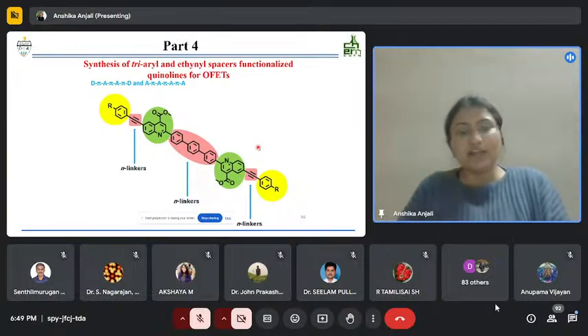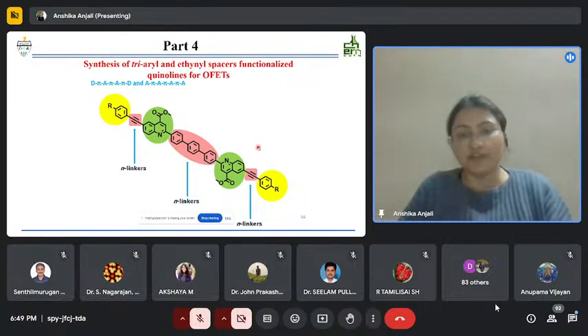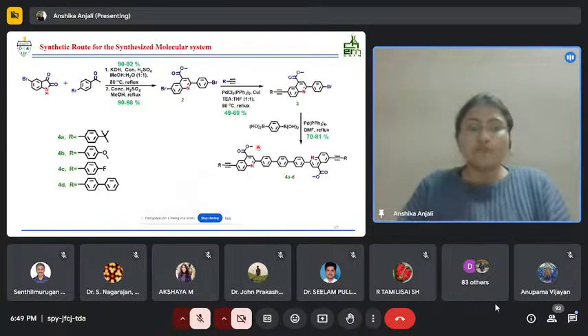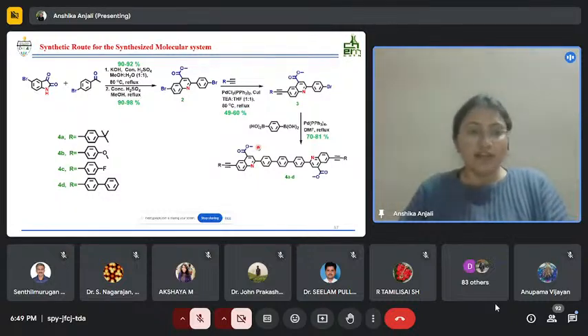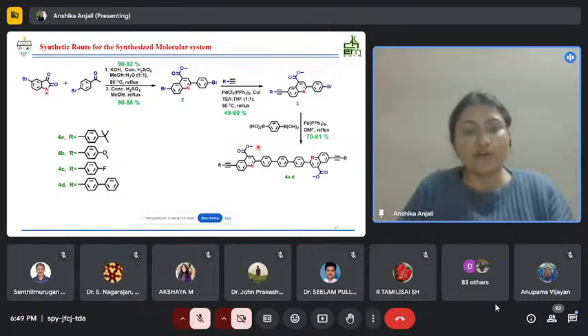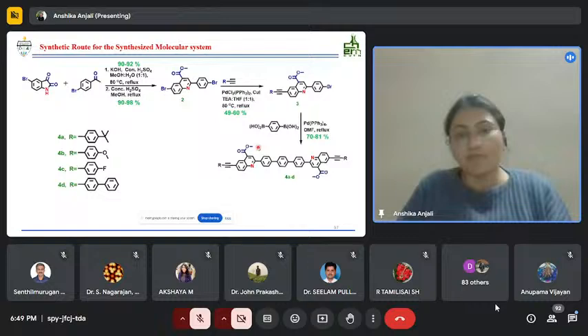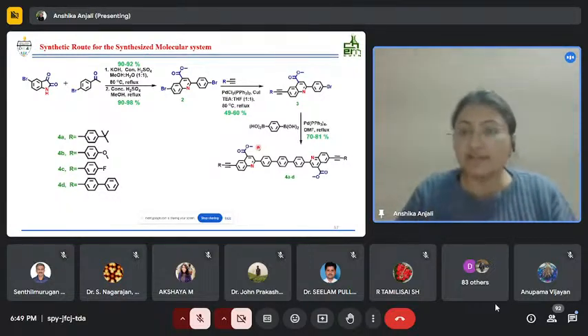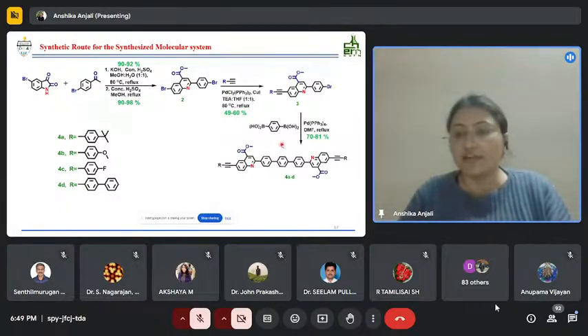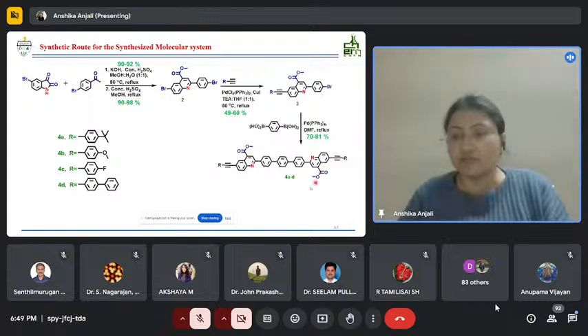For the fourth part, we have triaryl and ethynyl spacer functionalized quinolines. For the synthesis of these compounds, we carried out the Pfitzinger reaction followed by esterification. Then the compound underwent a Sonogashira cross-coupling reaction, which gave the third compound, which then underwent a Suzuki coupling reaction with 1,4-benzene diboronic acid to give the final compounds.